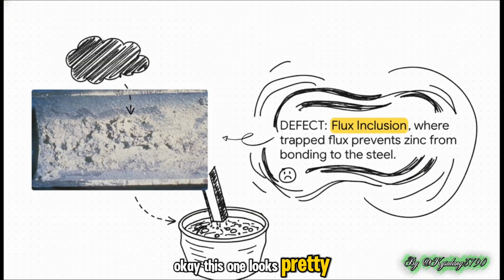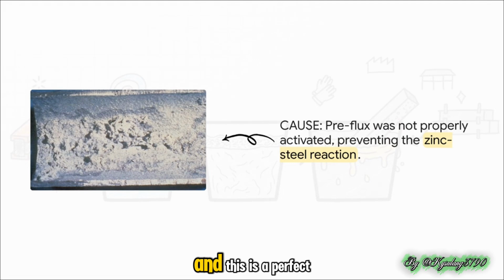Okay, this one looks pretty nasty. It's called a flux inclusion. That rough, kind of bare-looking patch you see, that's where the pretreatment flux got trapped underneath the zinc layer, and it physically stopped the zinc from bonding with the steel. And this is a perfect example of how critical that first cleaning stage really is. Any failure in the fluxing or cleaning steps is going to lead directly to a defect just like this. The zinc simply cannot bond to a surface that isn't perfectly prepared.